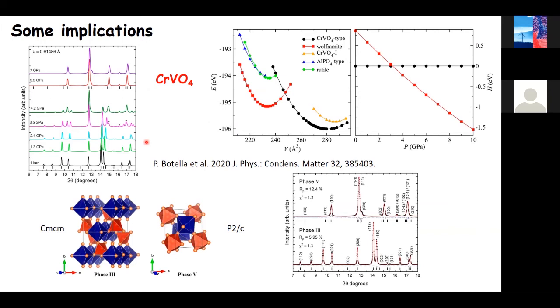If we go to chromium vanadate, it is a material isostructural to indium vanadate. Again, you see at ambient pressure, chromium vanadate crystallizes in phase 3, the same phase that indium vanadate crystallized in, which is orthorhombic. And we have seen by X-ray diffraction, so this is the refinement of the low pressure phase, that under high pressure, it goes to the same high pressure phase.